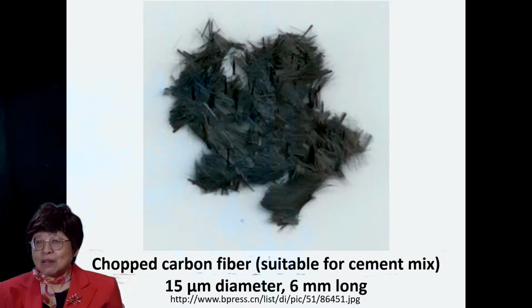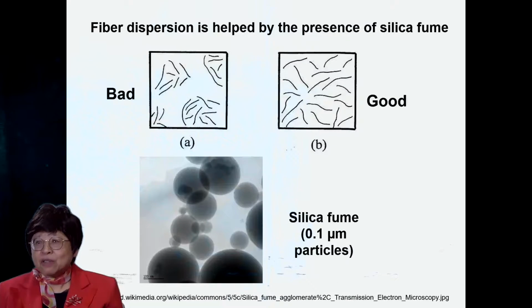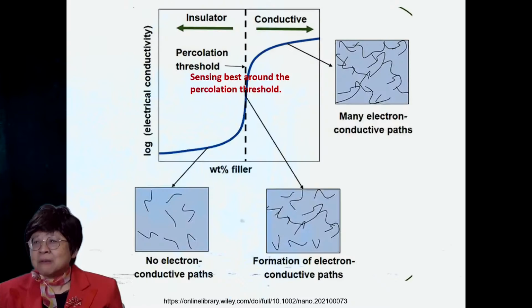Short carbon fibers look like this, and their dispersion in the cement is very important. And it turns out that the addition of silica fume or fine silica particles into the mix helps loosen up the fiber clumps.